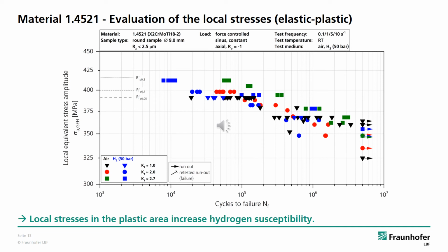Elastic-plastic finite element simulations were carried out for all tested specimen geometries to evaluate the local influence. The local stresses under hydrogen are constantly plotted in blue, and the fatigue strength results of the differently notched specimen geometries are plotted in the other colors. While in the range of lower stresses, the test results under air and hydrogen are still very mixed, a separation can be made in the upper range. Damage by compressed hydrogen occurs as soon as the stress is high enough and plastic deformation can appear. This finding is independent of the stress concentration factor and thus support effects do not seem to play a role.